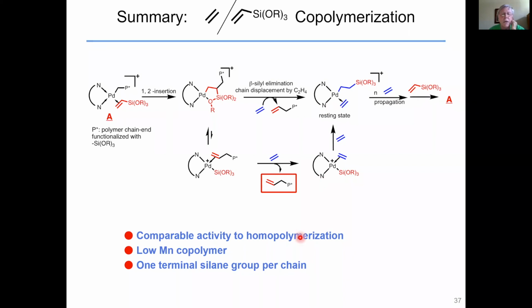Okay, so we have comparable activity to homopolymerization, essentially the same activity as we see if we incorporate the alpha olefins in the calculation, and we see one terminal silane group per chain, and we get low molecular weight copolymer. And as we increase the silane concentration, we trap this species sooner and sooner and cut down the molecular weight. So that's the overall mechanistic picture of this copolymerization.